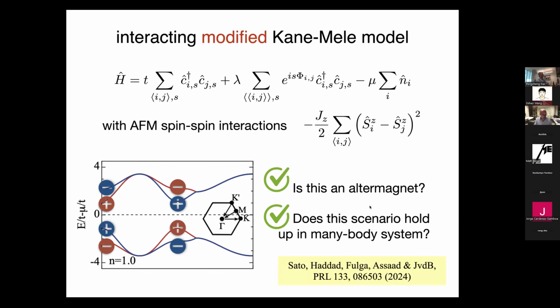That I would almost say no, but you'll have to look at the symmetry. If the Néel vector is along a symmetry axis, you might be in a case where you have a number of mirror symmetries. And that depends on the combined symmetry of spin and lattice, right? So it's not generic. It depends on each system. And if you have those mirror symmetries, they might act such that this excludes anomalous Hall conductivity.